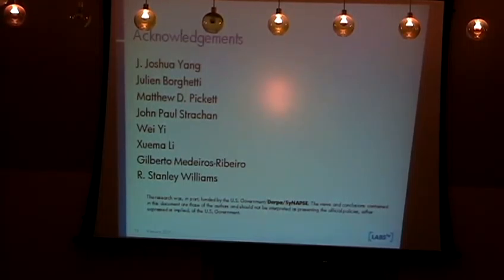Yes, please. Your retention looks like it's starting to die after a couple of weeks. So what do you do for a couple of years? Yeah, right now our research on low current switching is still at the very beginning stage. So we are trying to first understand the physical mechanism of those devices, and then we are trying to improve the retention by trying different fabrication methods. And the retention degradation is because of the diffusion of the ionic species? Yes, we believe so. But the initial transient is related to some trapping or other electronic effects.